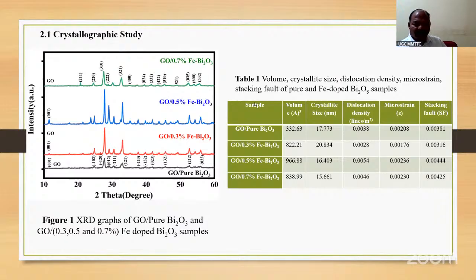Now you see the volume enhances up to 0.5 and then again decreases. The crystallite size again increased and then decreased up to 0.3, and the dislocation density first decreased, then again increased and then decreased. The dislocation density depends on the synthesis, and these are the stacking faults.